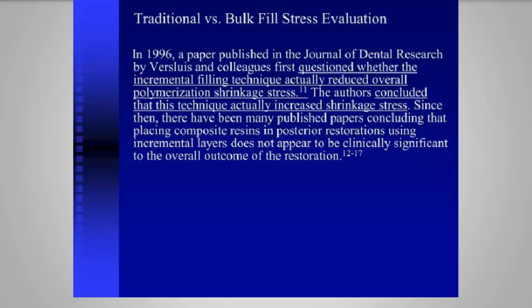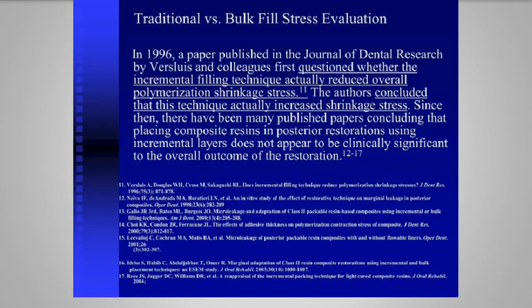Looking in the research papers in 1996, it's very interesting, because one of the first papers came out questioning whether the incremental filling technique reduced overall polymerization shrinkage stress. Well, this was in the literature in 1996, and they concluded that the technique actually increased shrinkage stress. Well, currently today, we've kind of flip-flopped, and now the literature supports that layering in increments of 2 millimeters actually decreases the stress. So even in the literature, that's come a long way, as you can see from the references cited there.